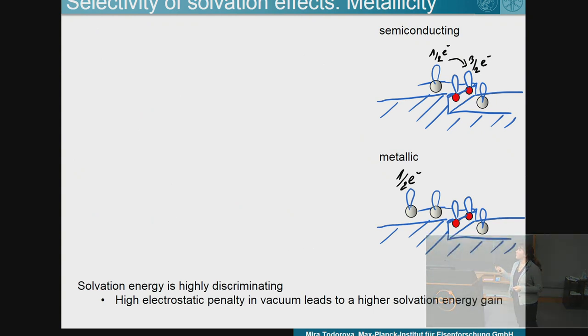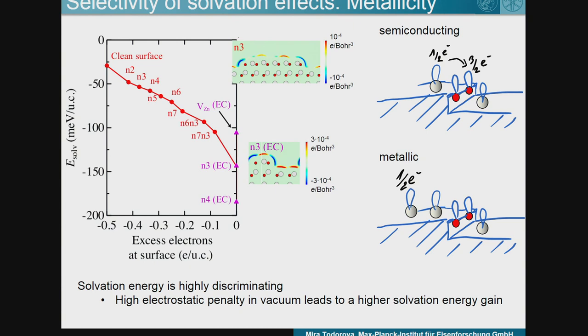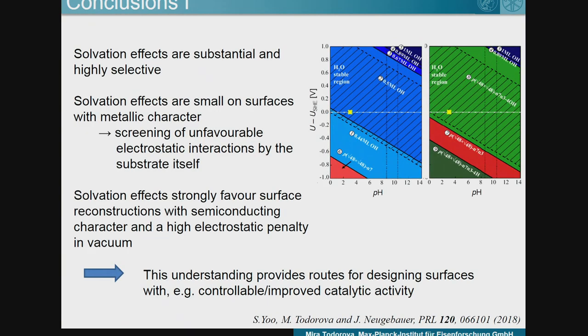There is a second effect. We do have a few structures where we don't have the same number of dangling bonds of zinc and oxygen. So we still retain some electrons at the surface. So these are metallic states. Within this plot, these are the metallic structures. On this side, we have structures which are semiconducting. And as you can see, as the structures become more semiconducting, there is also a strong gain in solvation energy, which means that structures with non-metallic surfaces are really favored by the solvent as compared to metallic surfaces.